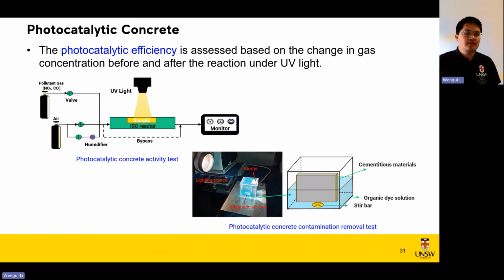How to evaluate the efficiency of photocatalytic concrete? Here, the efficiency is usually assessed based on the changes in gas concentration before and after the photocatalytic reaction, and the samples are treated with UV light. At the same time, the degradation rate of pollutants is calculated by the changes in solution concentration before and after the test.